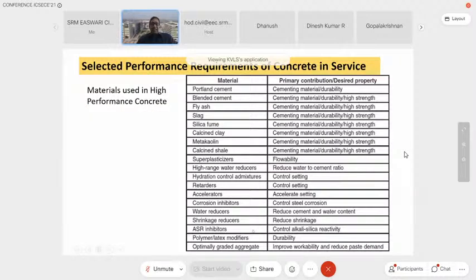And the material palette that we have to use now has also expanded tremendously. Conventionally, if you look at it, we only had Portland cement. But now we are bringing in more and more supplementary cementitious materials: fly ash, slag, calcined clays, metakaolin. These are all finding their way into cements. And our admixture basket has grown tremendously. Now we are using different types of admixtures. We're blending admixtures so that we're able to target specific improvements in performance of the concrete.